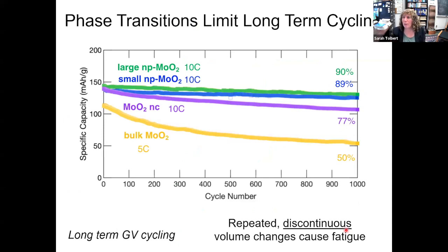Okay, how does that help us with our cost of energy storage? Well, if you don't have phase transitions, you don't rearrange the atoms every time, and that results in much longer cycle life. If you look at the bulk material, after 1,000 cycles, it's lost 50% of its capacity. If this was your cell phone and you charged it every night, that would be 3 years and your battery would be pretty useless. The nanoscale materials, after 1,000 cycles, still have 90% of their capacity.